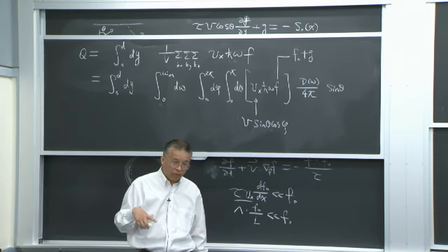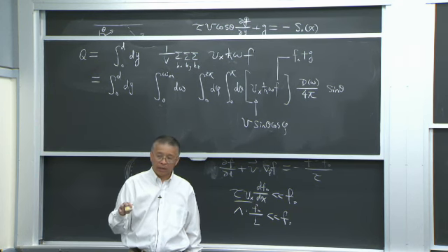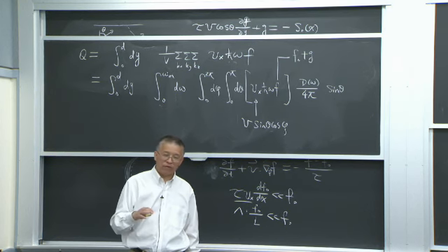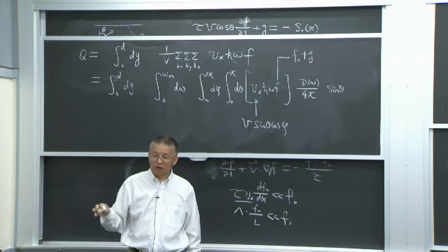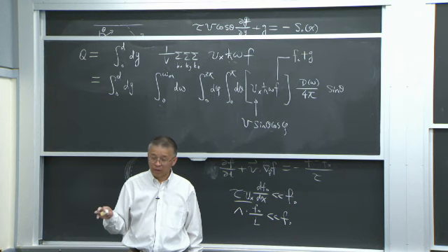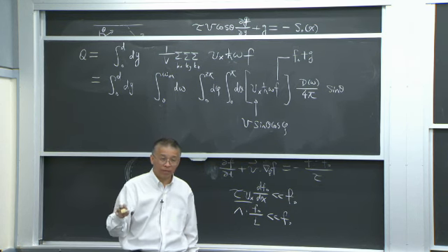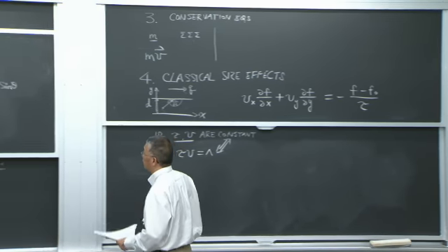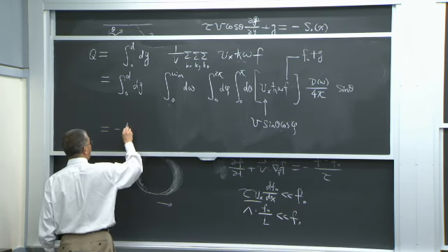You go to fluids problem, right? When people do rarefied gas dynamics, they typically take constant tau. You do heat transfer, people typically do constant mean free path. I don't see a very good justification for those choices, but because of those different choices, the final result looks slightly different. Okay, and so if I do this, and of course eventually you can write this as your minus k,